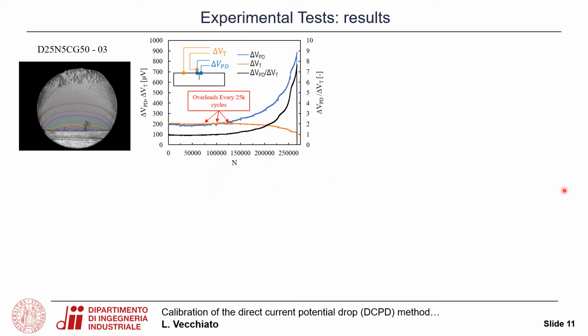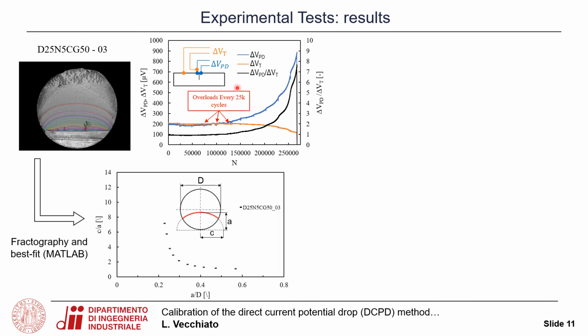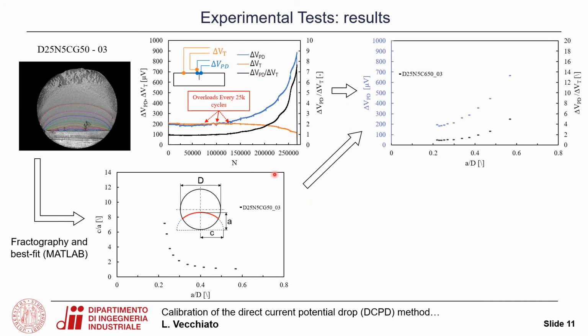Here we are seeing an example relative to specimen number 3. The image reports the fractography of the fracture surface of the specimen, and this chart reports instead the potential drop value as a function of the number of cycles. In blue the main signal, in orange the reference signal, and in black the normalized one, so the ratio between them. From fractography and the best fit in MATLAB, it was possible to obtain the change of the aspect ratio with respect to the normalized crack depth for each benchmarked crack front. Then, combining the DCPD signals and this result, it was possible to obtain the experimental DCPD calibration curves both for the normalized signal in black and for the main signals in blue.